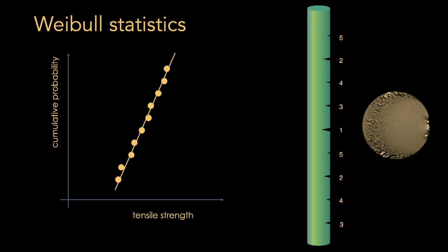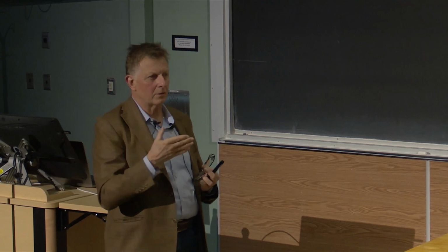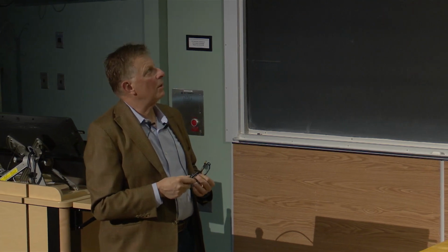The way that's being illustrated: researchers, the ones that started in 1920 and after, draw fibers, and the moment that you draw it, you can measure the strength, and it's pretty high. And then after a day or after a week, after a month, that strength has reduced. Because the glass surface is exposed to the environment. It could be mechanical, that it's being rubbed against something, or bent. But typically it's the humidity in the environment. Water is very aggressive to glass surfaces, and so you create these small imperfections.